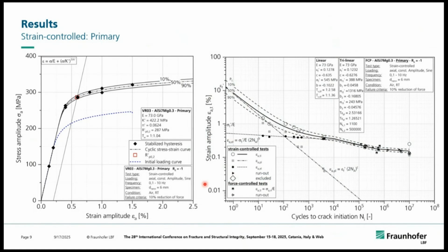Let me go over to the strain-controlled fatigue tests. You see, first of all, the primary alloy. What we can state here is that we have a strong cyclic hardening effect. We see here the stress-strain curves from the evaluation of the test results in comparison to the initial loading curve, and we see a strong cyclic hardening effect. This was present for all those alloys, but the strongest effect came from the primary alloy. And you see on the right side the evaluation of the strain life curve with this trilinear approach, where we accounted for a knee point in this regime as the first step.